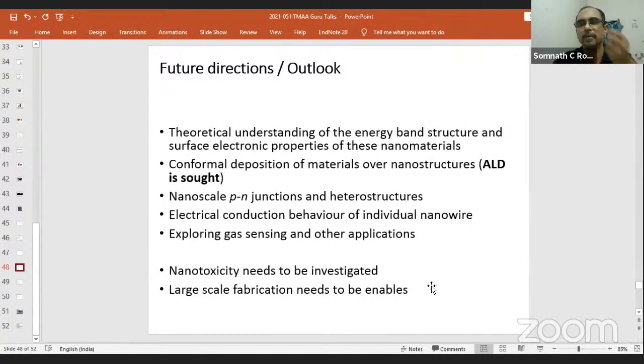For example, when we put talcum powder or any cream, they have very fine particles, not exactly nanoparticles, and they penetrate a little inside the skin through the pores, but they do not create any harm, because they have very low toxicity and they are biocompatible, or at least skin compatible. So this kind of investigation needs to be done as we explore new nanomaterials. What if I want to make them on a bulk scale for different applications? Invariably humans and others will be exposed to them.